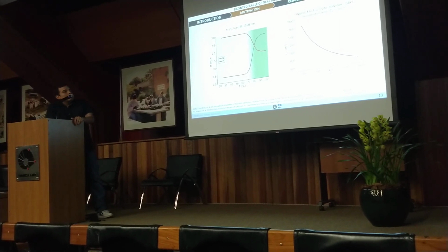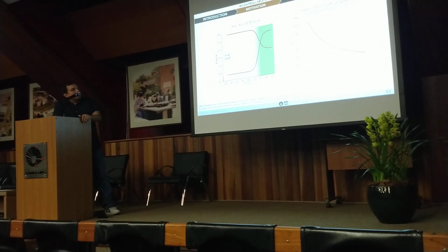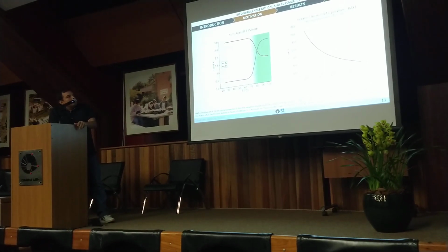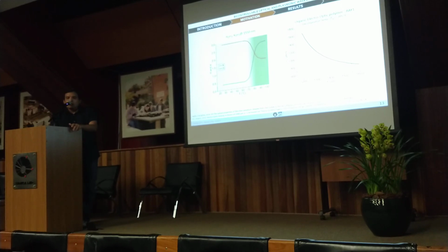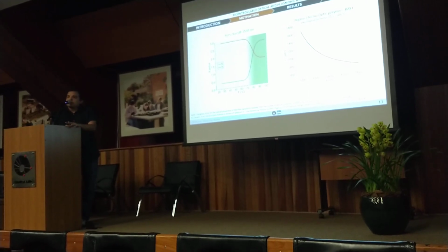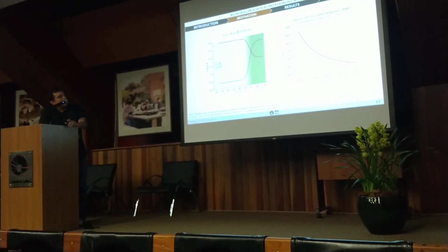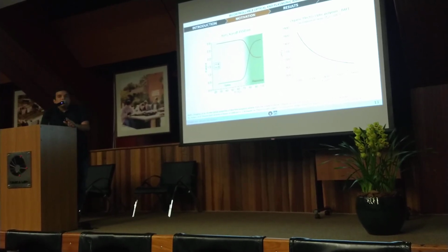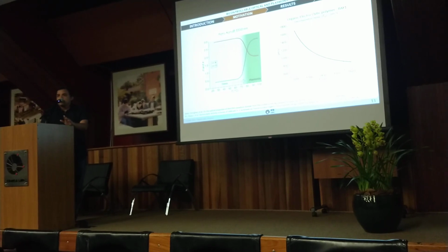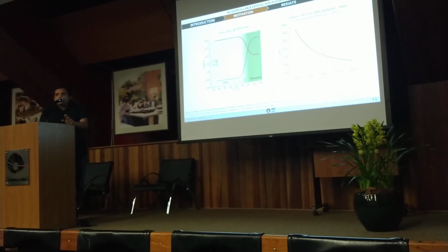In our study, at 1.55 micrometers, we have 690 picometers per volt. The other question I want to ask is, if this material changes from dielectric to metal, can we change from optical to plasmonic at the same wavelength? That is our result shown.